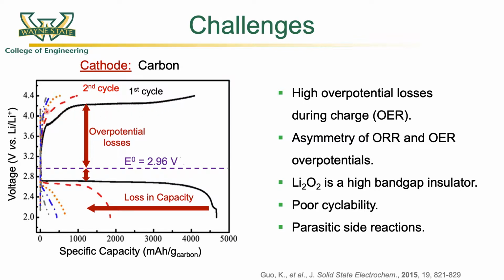In other words, what this plot suggests is you're putting in about 4.4 volts of energy to charge the battery while getting only 2.7 volts out, thus making these systems less efficient in nature. In addition, this high overpotential loss during the charge cycle results in triggering of parasitic side reactions, which is seen as a loss in capacity over cycling, and almost there is no capacity left by the time the cell reaches the fifth cycle. Therefore, there's a need to understand the catalytic processes occurring at the cathode that can reduce these overpotential losses.